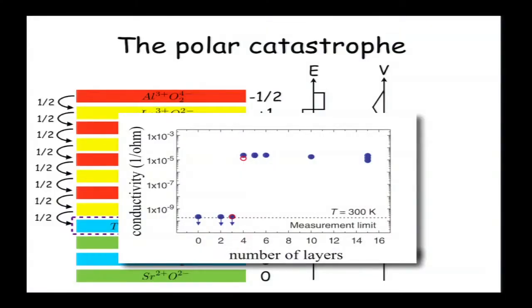All of the interesting physics that I'm going to speak about is actually coming from this interface layer where all the charge was transferred to. And that explains what occurs at the interface from electrostatics, but we can see it also in experiment. We can see here a measurement of the conductivity as a function of the number of layers of lanthanum aluminate. As long as there are three layers or less, the system is not conducting, as I said, just insulating. However, at four layers and more, the system becomes conducting, and actually we can see that it's almost independent of how many layers are put on top of the strontium titanate.